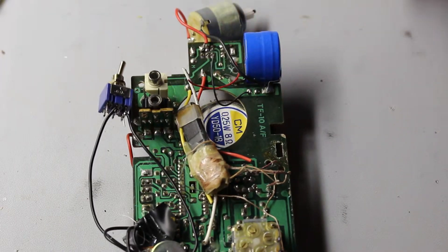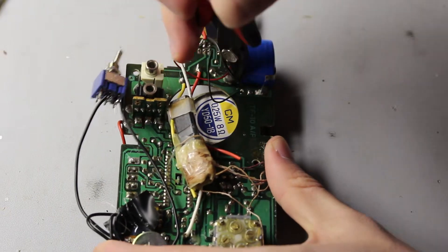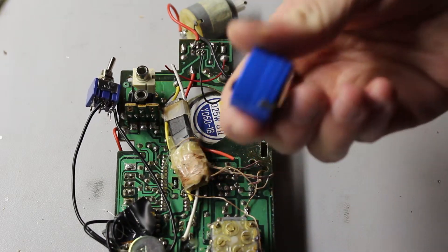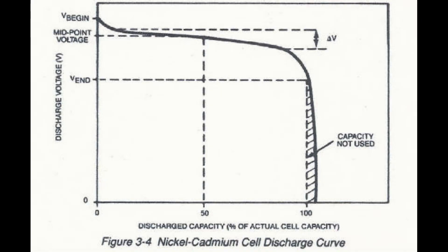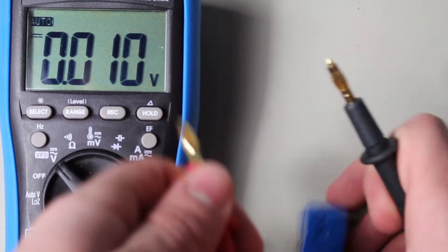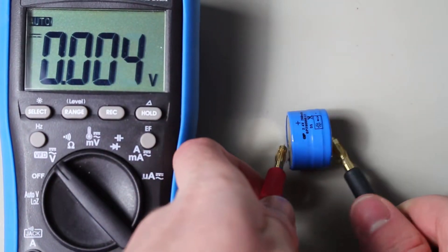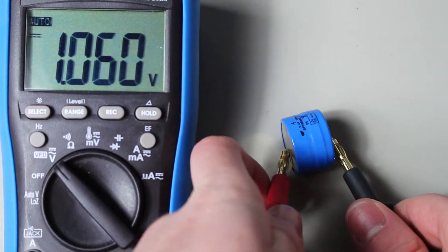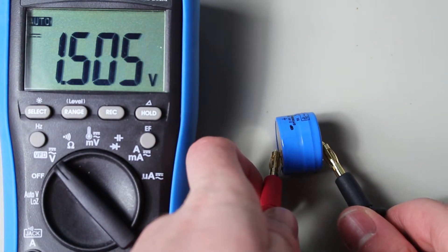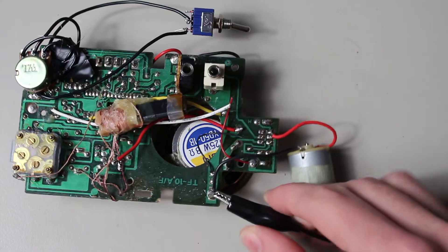So, I took the battery out of its spot for inspection. Since this is a two-cell NICAD, we should be getting about 2.4 volts. These batteries have a very stable voltage throughout their capacity, so a dead battery should be a very low voltage. Measuring the voltage reveals that we get a voltage of 1.06 volts. So about 0.53 volts per cell. That is a considerable amount lower than the usual 1.2 volts. Not to mention that the IC requires at least 2 volts total to properly function.